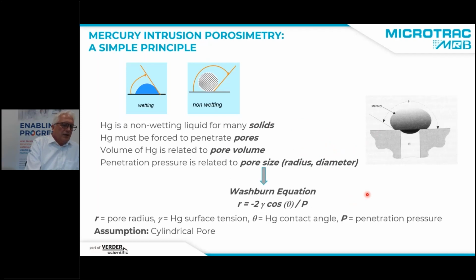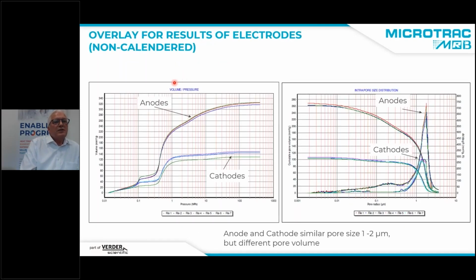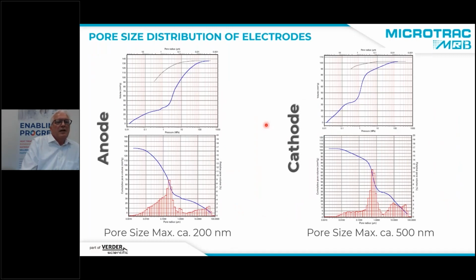Some applications on electrodes. These were here non-calendared cathodes and anodes. This example shows similar pore sizes of these anodes and cathodes, but you see here the pore size distribution has a very different pore volume, which you can see on the left-hand side, for example. Another example is that we do have different pore sizes of the anode of about 200 nanometers shown here, or cathode of about 500 nanometers. So this is easily detected with the BELPore mercury intrusion porosimeters.